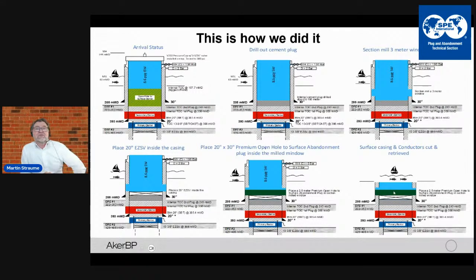And after a year or so, we actually cut the casing, because we had gotten such good results on the D annulus that we could cut it. But we cut it actually in the middle of the sea. The sea depth is about 70 meters here. And we cut the conductors, the surface casing and conductors at about 35 meters. So there's still a chimney of 30 meters standing up there.